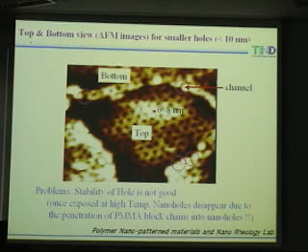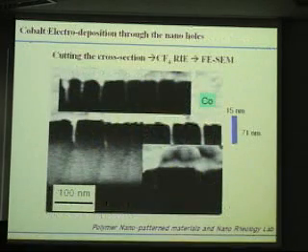Also, sometimes we see the channel in this way, so we can see the hole is connected to the bottom of the film. That is a very beautiful result. But the problem is this hole is not thermally stable. Once the film is exposed to a high temperature, the chains in the PMMA block can penetrate the hole, and the hole suddenly disappears.